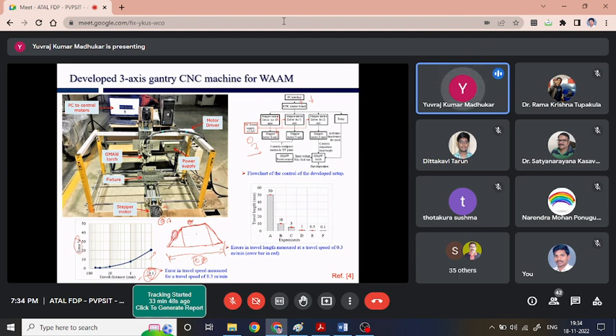So practically, we might be getting like this, and it may not even be achieving the peak velocity we will be commanding. So here we could see when we are giving a travel length of nearly 50 mm, the percentage error is less than 1%. However, when we are going for a distance of 0.1 mm, the percentage error is nearly 20%. So the bottom line is, for the shorter distance, the percentage error is going to be more.